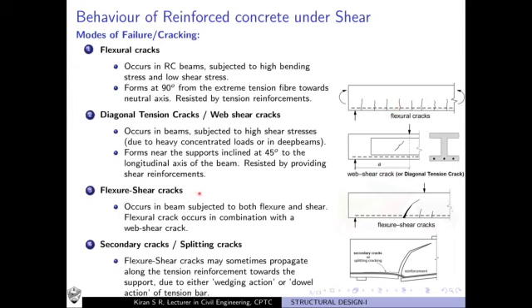So those cracks occur in beams subjected to both flexure stress as well as shear stress. So in those beams where flexure stress as well as shear stress are substantially high, flexure shear cracks occur. And the way they propagate is also a combination of both. Initially, the flexure crack develops at the extreme tension fiber, nearly perpendicular to the neutral axis. And as it propagates further near the neutral axis, it tends to incline and achieve an angle closer to 45 degrees and become a shear crack. So initially it is a flexure crack and later it becomes a shear crack. So a combination of both will give you a flexure shear crack.